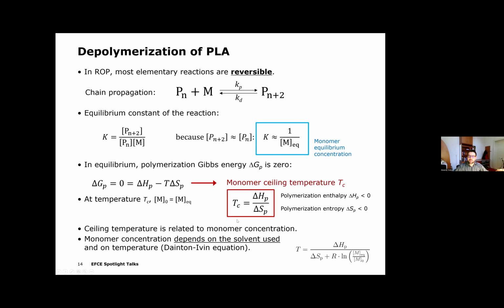Therefore, we can actually calculate the so-called monomer ceiling temperature, because the enthalpy of the polymerization as well as the entropy of the polymerization are both negative numbers. So theoretically, for each of the propagation steps, for each monomer, we have a ceiling temperature that represents the temperature at which the rate of the forward and backward reaction is the same. So we cannot polymerize anymore.